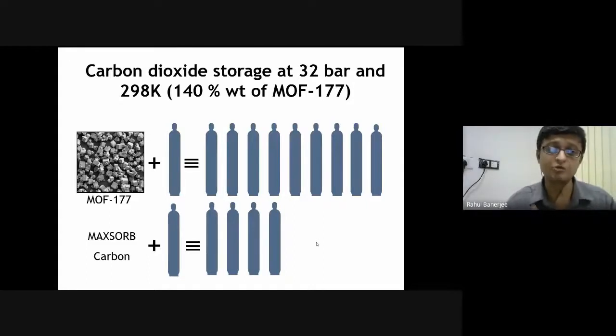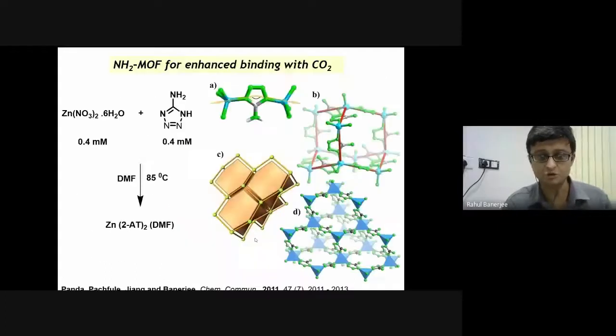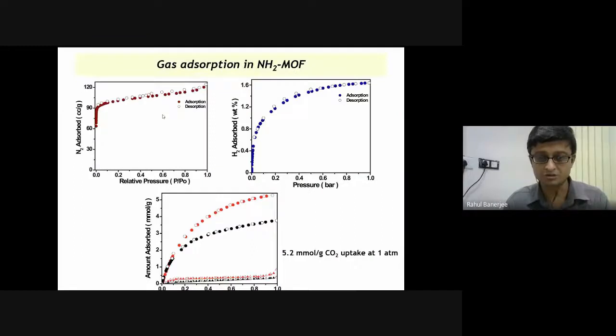So similarly, now we are trying to make some of these MOF materials, put them into the canister, and try to see whether it works or not. I will not go into too much technical nitty-gritty, but I want to show you that we use the same amine and acid technique, exactly the same thing. We just put it on a MOF backbone, created this powder full of amine, and when we tried to store the carbon dioxide, we figured out that it stores a very nice amount of carbon dioxide.